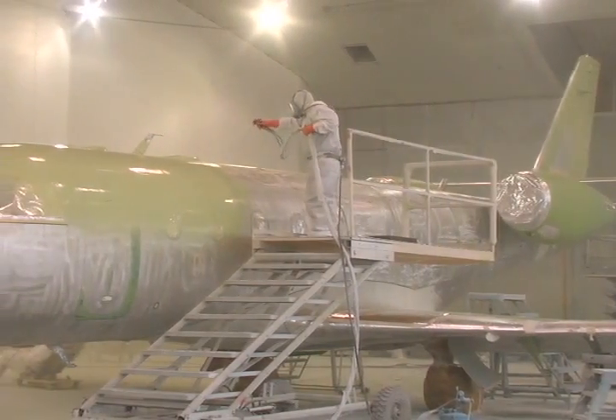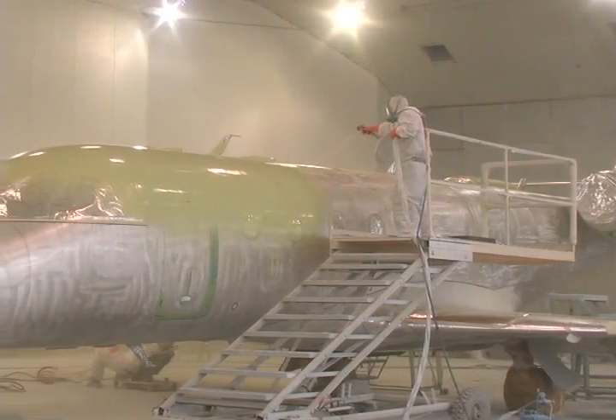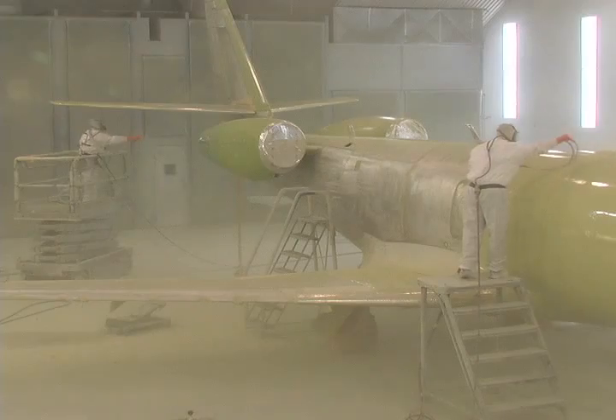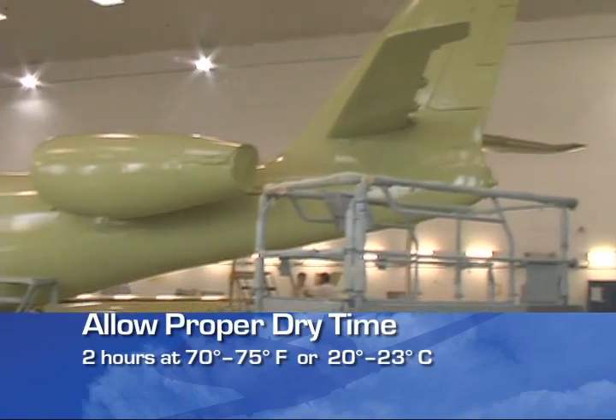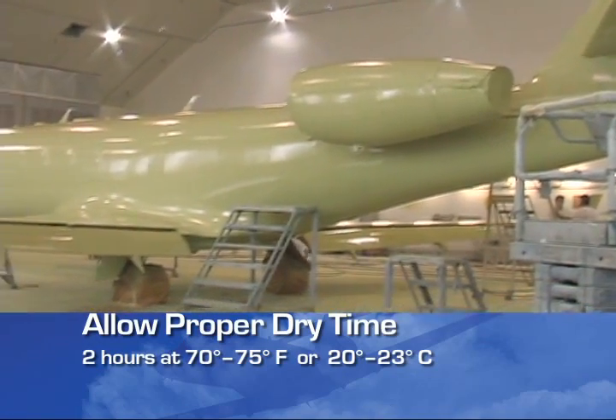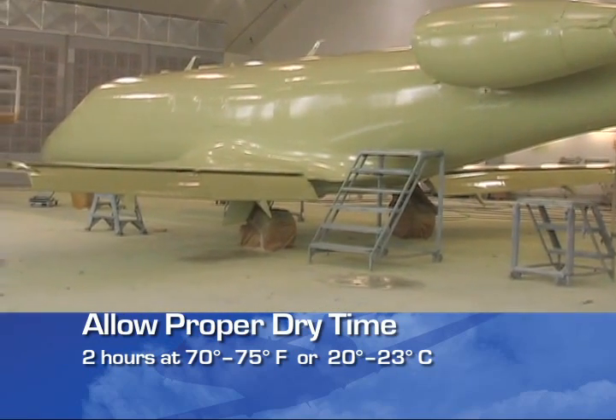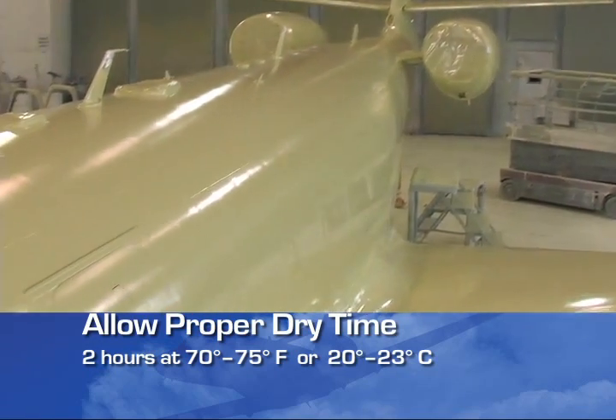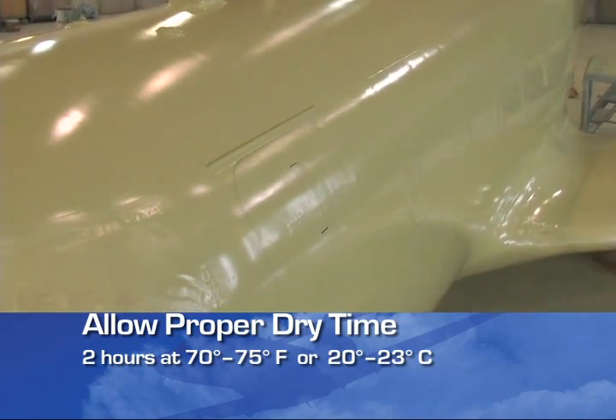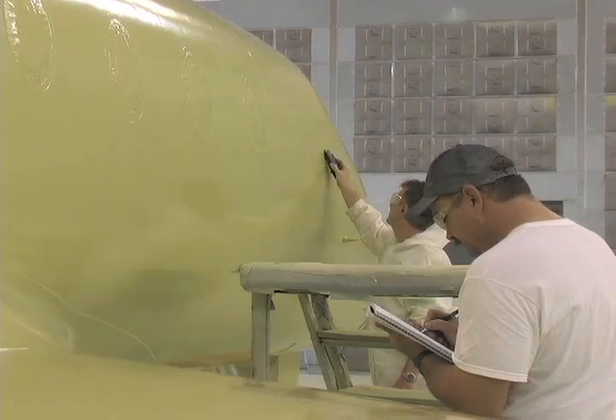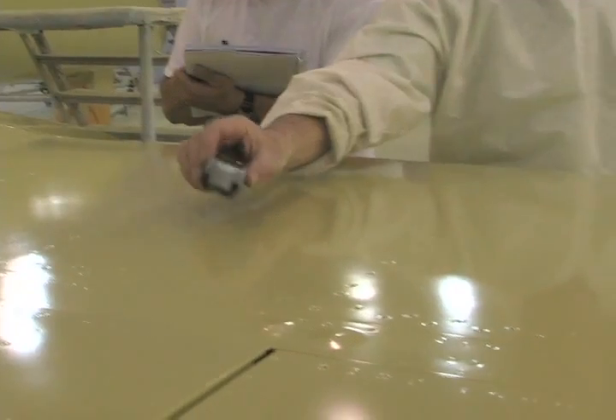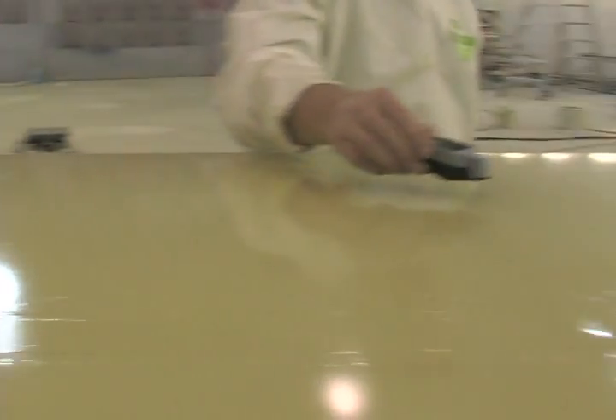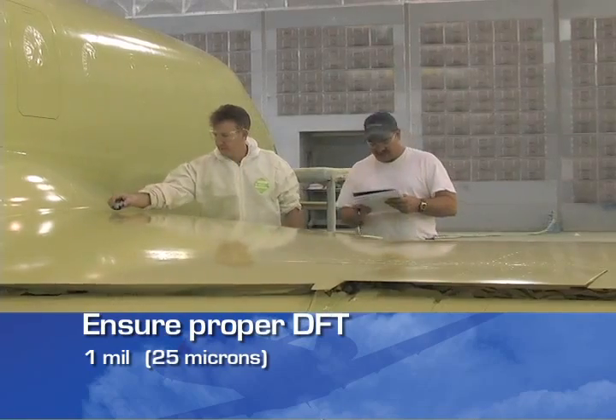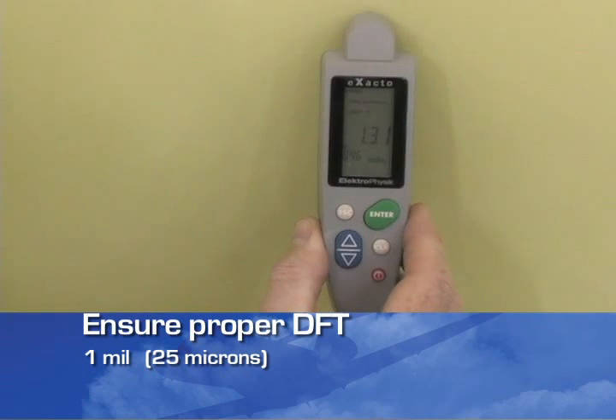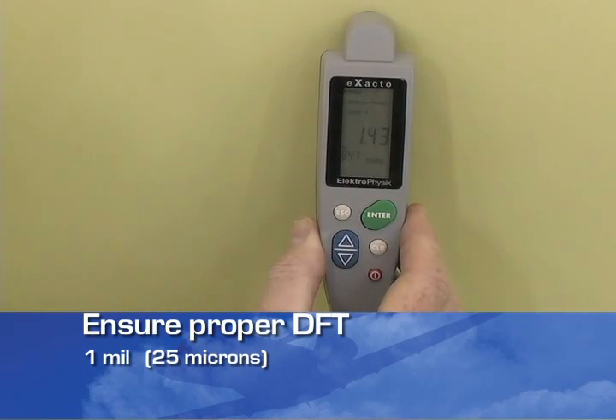Apply one light, continuous, closed film coat. Always ensure the primer is thoroughly dry before overcoating. You should allow at least 2 hours for drying in a hangar that is at room temperature. After the primer coat has dried, you should take dry film thickness readings at all areas of the aircraft. The primer coat should be approximately 1 mil or 25 microns dry film thickness.